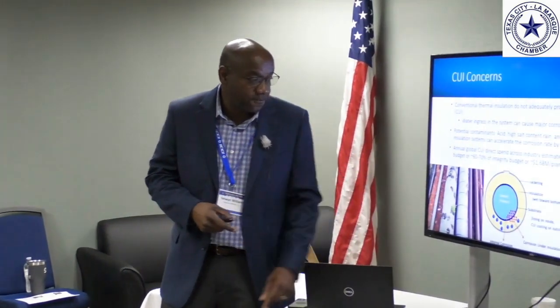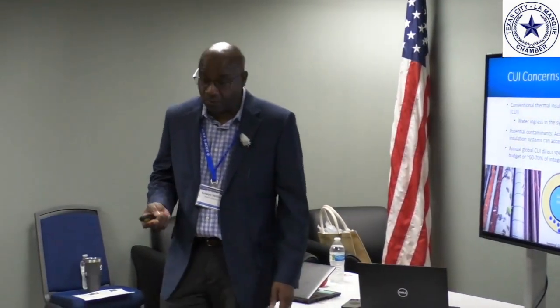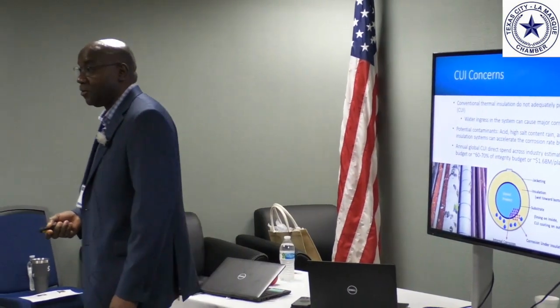The normal systems that we use today for CUI are mineral wool, calcium silicate, and some man-made mineral wool. But they all have the same concerns. They all are installed the same way. You have a product stored in a tank or transported in a pipeline, and there's a lining in the interior of that substrate. The exterior is coated with a CUI coating. Between the coating and the cladding, you have an insulation product, mineral wool or calcium silicate. And you typically would have accelerated corrosion if this material gets wet, and it does get wet. There's no way you can actually remove that water completely.